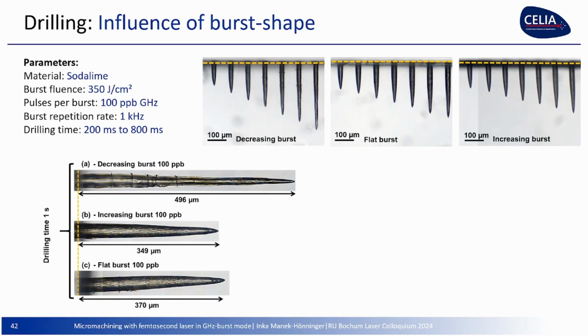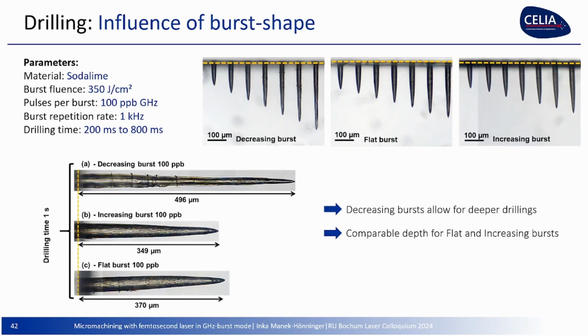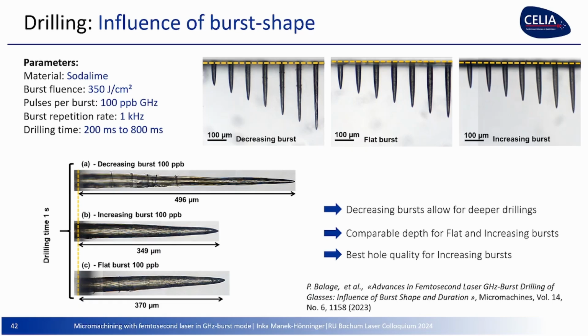However, the quality of the hole is the best with the increasing burst. And the flat burst seems to be a good compromise between speed and quality. Really, the best quality is the increasing burst. So if you go slowly in the beginning, this is easier for the material. There's not much heat affected, which is also logical.